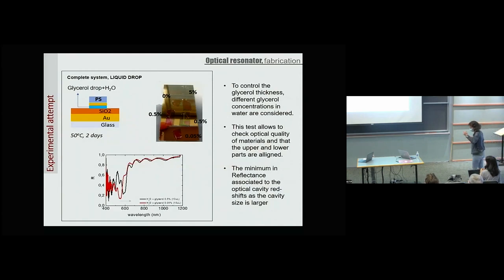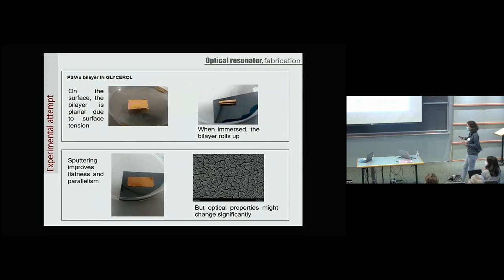So we started putting a drop of glycerol close to the dry optical resonator, so that by infiltration, because we are going to have these repulsive Casimir forces, we thought, okay, maybe the glycerol can come in between the levitating part and the substrate. We had a drop of water with some glycerol in a different concentration, and then we evaporated the water, so everything was glycerol down the sample. We also characterized the reflectance, and we could see that the minimum was moving, so everything looked okay. But then we wanted to immerse the whole thing in glycerol, and then things started to mess up.